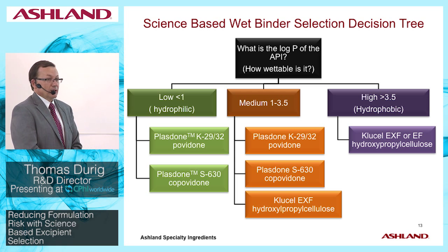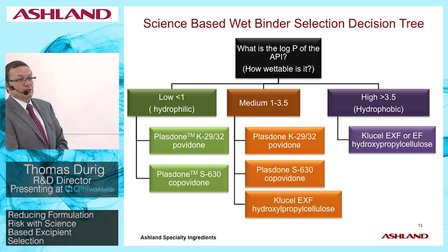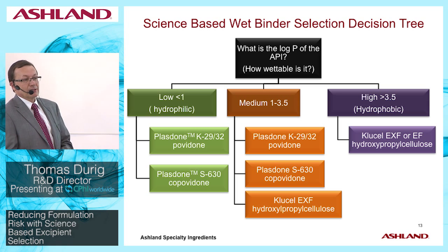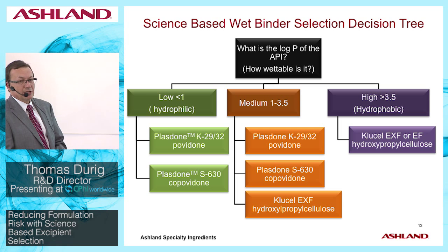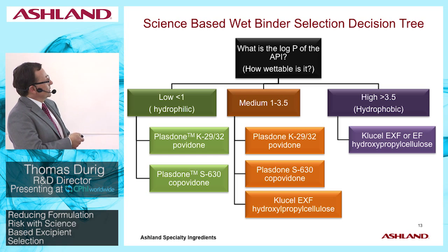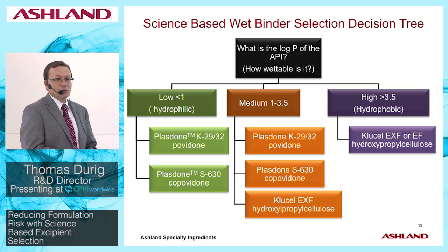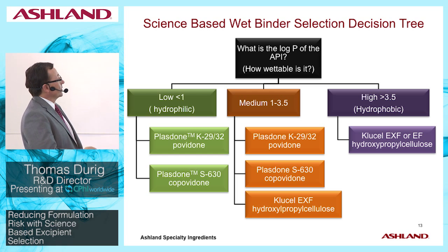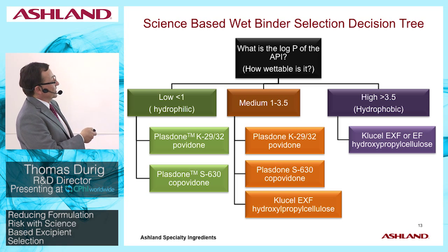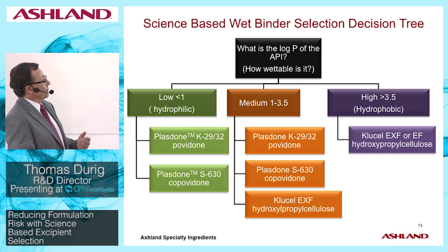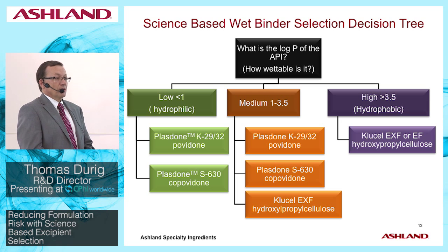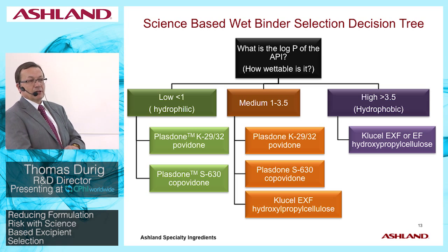The next case study is one where I'd like to look at reducing alcohol-induced dose dumping in modified release. This is an area that's attracted increasing attention over the last 10 years or so. A triggering case for the FDA was in 2004 with the introduction of a new hydromorphone extended-release capsule. This capsule contained extended-release beads, which comprised alcohol-soluble excipients like methacrylate copolymer, and ethyl cellulose and stearic acid, which are commonly used as controlled-release film coatings because they're relatively water-insoluble.